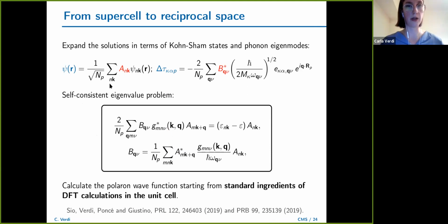This sum over n is only over unoccupied states, or occupied if we're describing a hole. This is because, as I said, we're making the assumption that the valence states are not affected by adding this electron in the supercell. And so this means that our polaron state needs to be orthogonal to the valence states. So this summation can only include conduction band states.